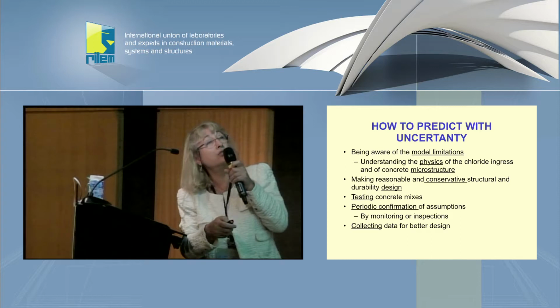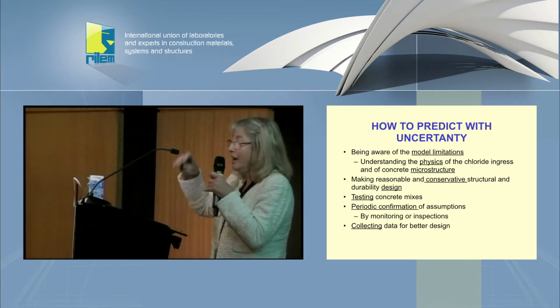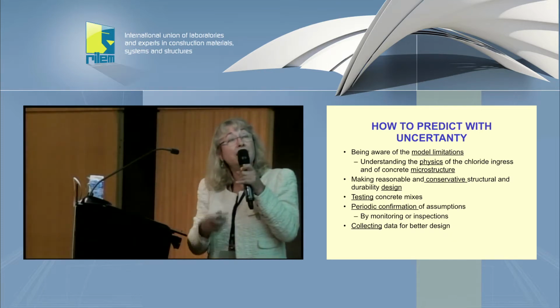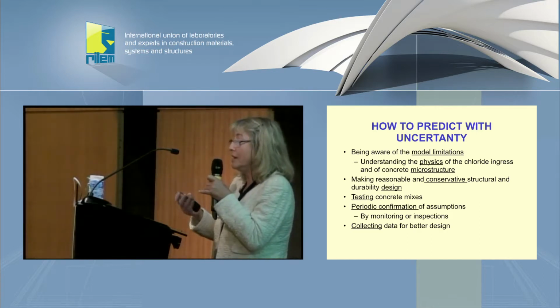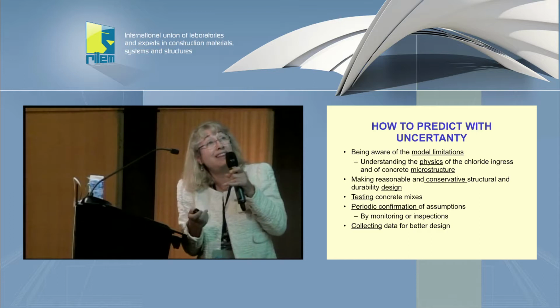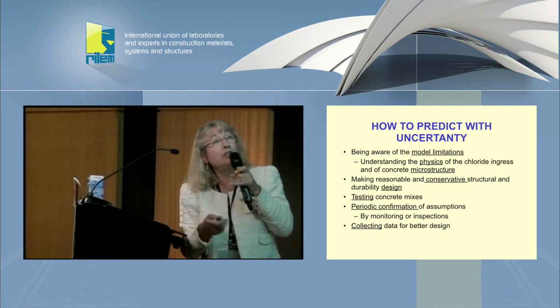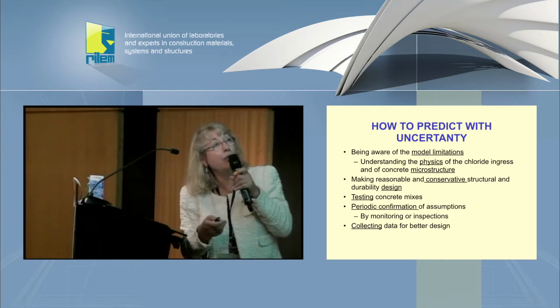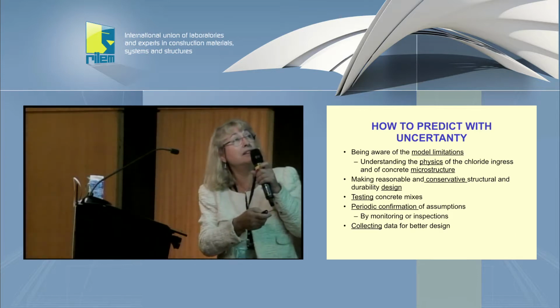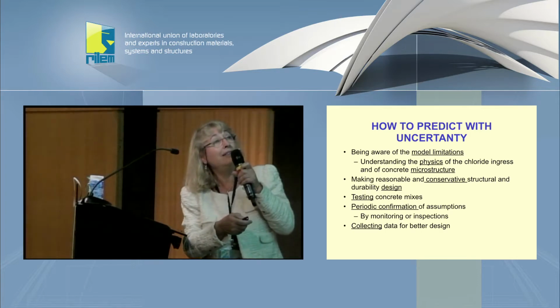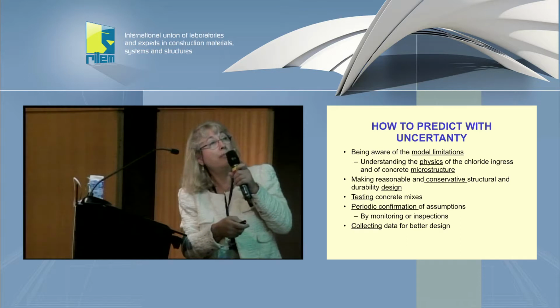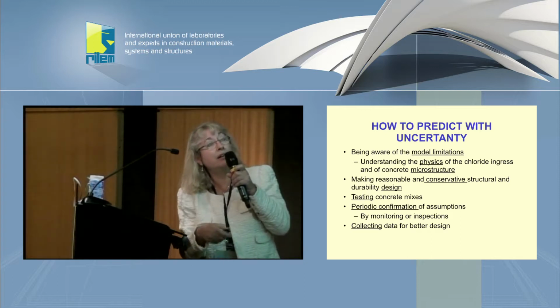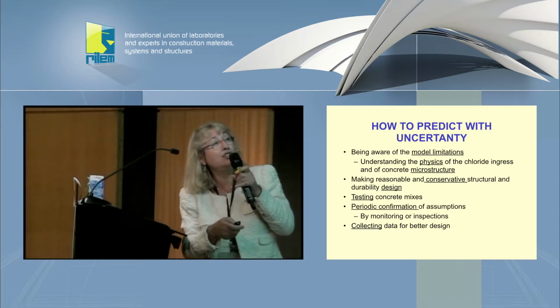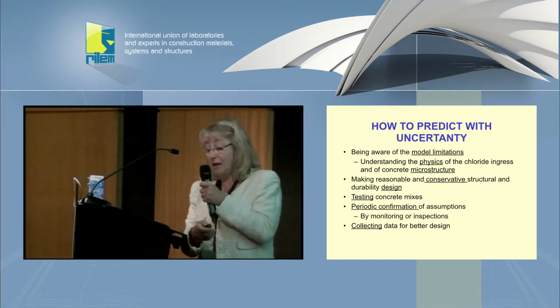Well, the other is being conservative, making a reasonable and conservative structural durability design. You cannot make a very strange or very slender structure if you are in a very aggressive medium. It's much better to be conservative, even if maybe the aesthetics are not so good, than to have maintenance and problems too early. Testing concrete mixes for durability is necessary, as is periodic confirmation of the assumptions by monitoring or by inspection, just to be sure that things are going as assumed during the initial time, and collecting that data for better design.